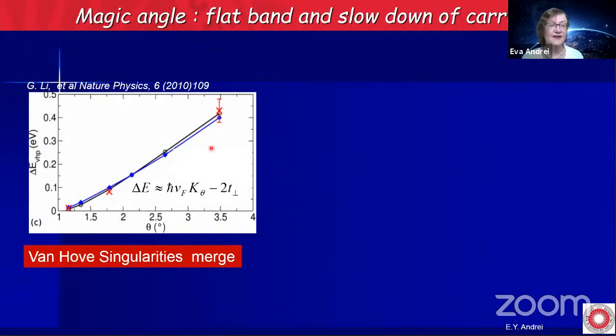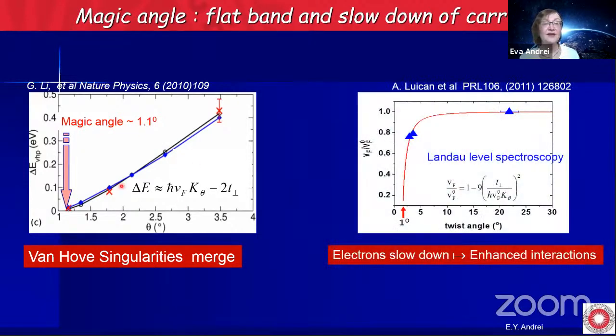So here we plot the distance between those peaks, which we call Van Hove singularities, as a function of twist angle, and we see that at about 1 degree, it closes down. And that's what we call the magic angle. This was named actually after our paper. And then we can also measure the Fermi velocity, the velocity of the electrons, as a function of twist angle by using Landau level spectroscopy. And here we have a few points. And the red line is the theoretical calculation.